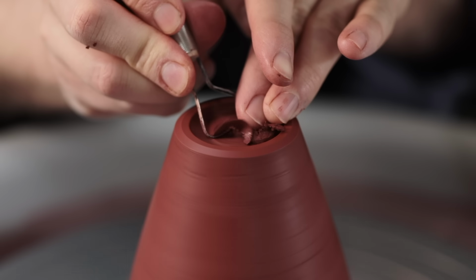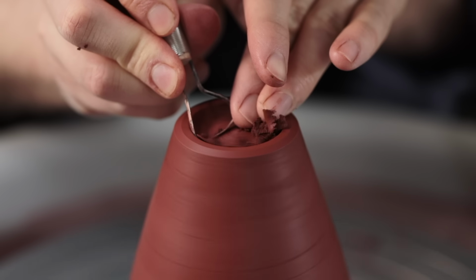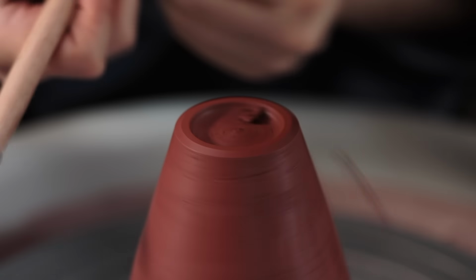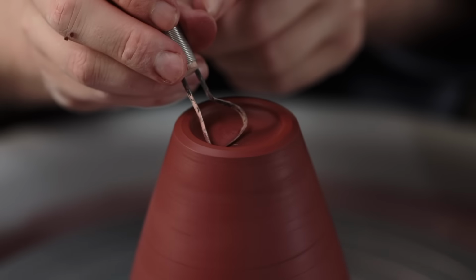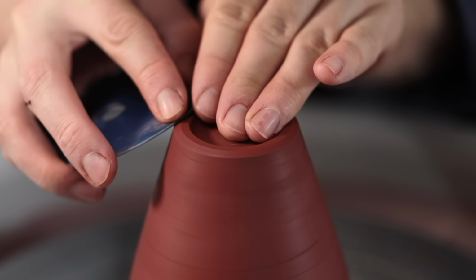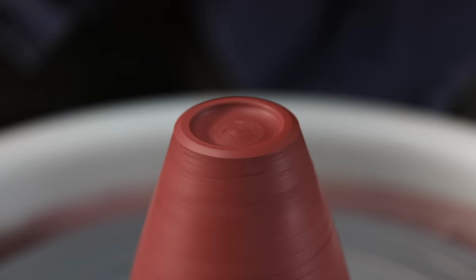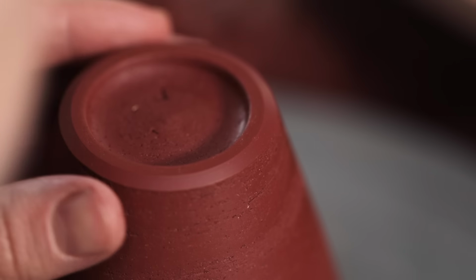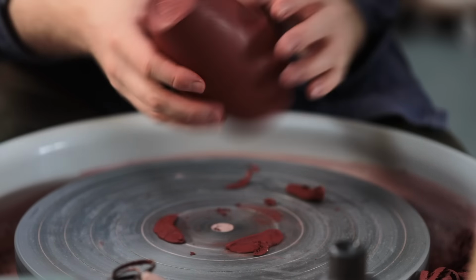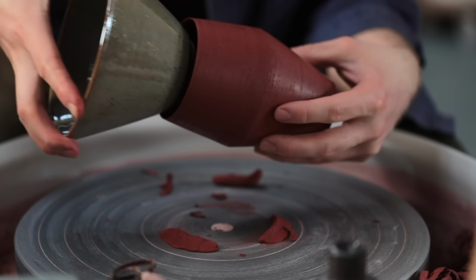I couldn't really feel the bronze inclusions when throwing these pots, but I could certainly feel them scraping against the metal blade when trimming them. Sometimes they get caught and are dragged across the surface, leaving long gouges in the clay. It can't be avoided entirely, but if it does happen, I have to burnish and remove them, as otherwise the thin glaze that will eventually coat these pots might settle into them.